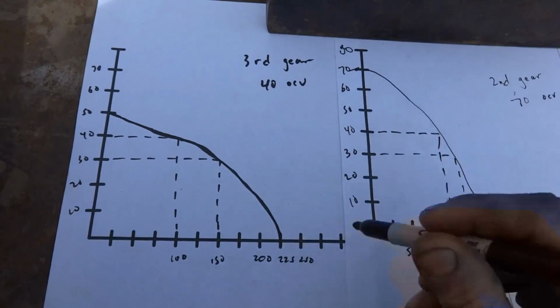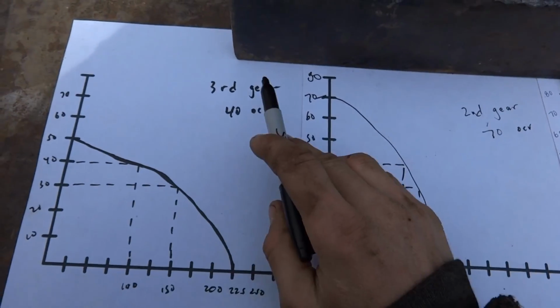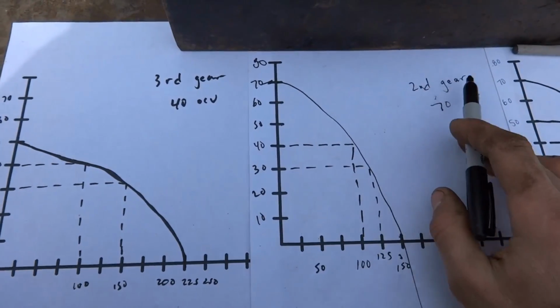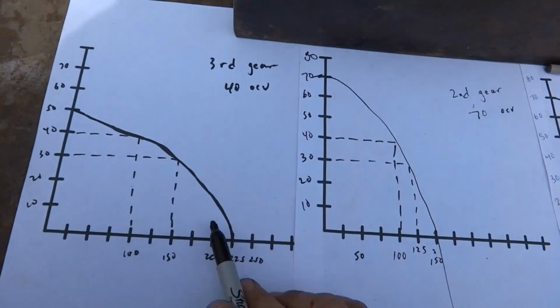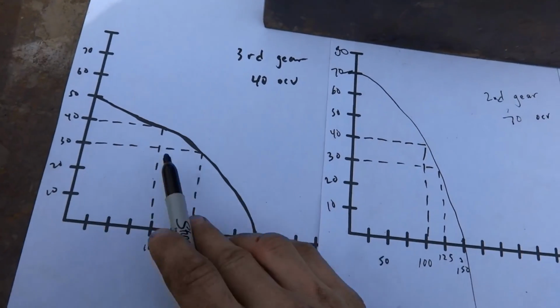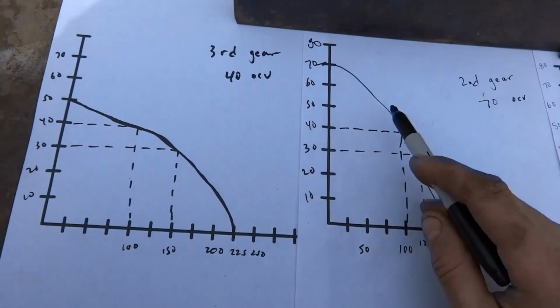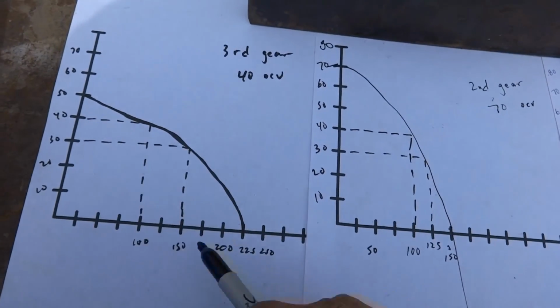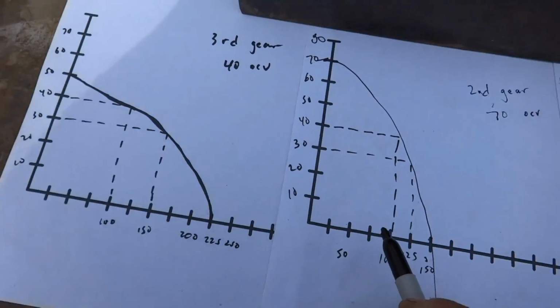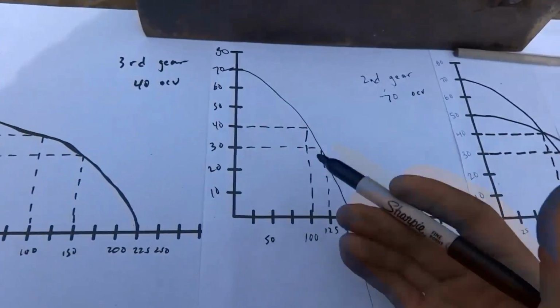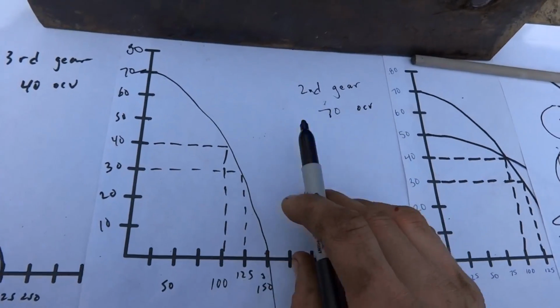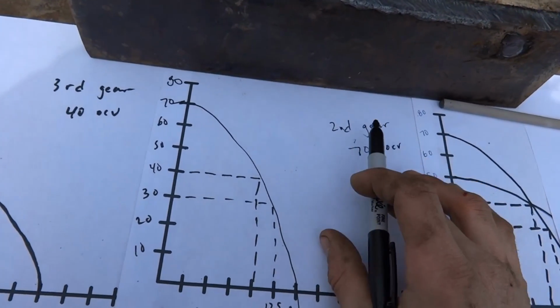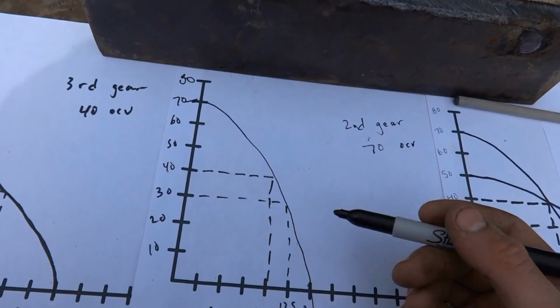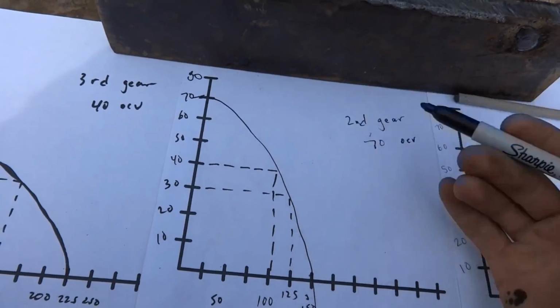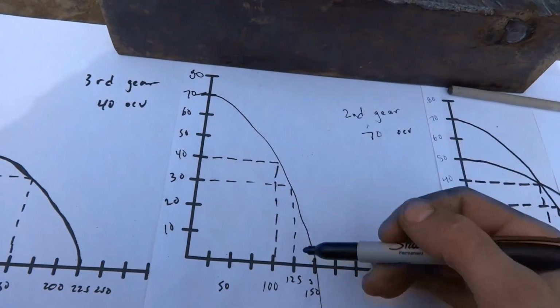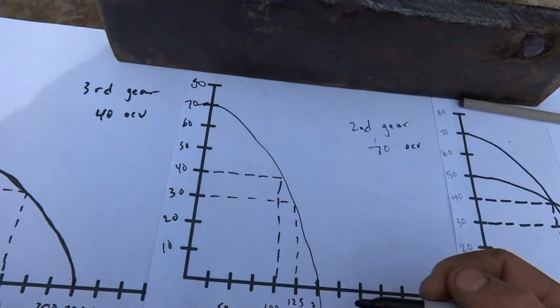So this is what you need to know. These are the two volt amp curves: high amperage, low voltage, and low amperage, high voltage. You see the volt amp curve. You see the change in the amperage and the voltage. This is a drooping volt amp curve. But you see the change in the amperage and the voltage using arc length manipulation. You're also able to hold a tight arc. If you're more volt heavy, then you have to give arc length so you don't snuff out the electrode. That increases the voltage even more and drops the amperage even more. You lack the burn off rate because you're volt heavy already, and you're adding arc length manipulation, which increases voltage.